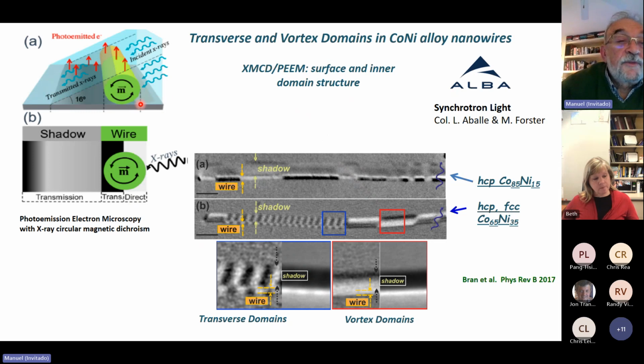We have used this technique of photoemission electron microscopy with X-ray circular magnetic dichroism, and you see here a schematic view of the cylindrical nanowire. Some of the incident rays are reflected. These reflected or photoemitted electrons give us information of the magnetic structure, the distribution of magnetic moments in the surface of the nanowire. But some of the X-rays are transmitted. These transmitted X-rays give us information of the internal part of the nanowire. So we get information of how the magnetic moments are distributed inside the nanowire.